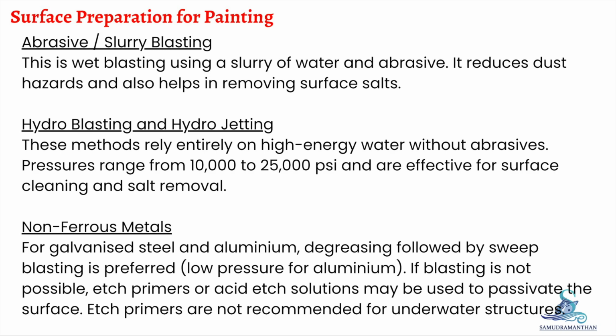Hydroblasting and hydrojetting take abrasives out completely. These methods rely entirely on the energy of water striking the surface, with pressures ranging from 10,000 to 25,000 psi. They are very effective for cleaning surfaces and removing salts. For non-ferrous metals, the approach changes slightly. For galvanized steel and aluminium, degreasing followed by sweep blasting is preferred, at low pressure in the case of aluminium. If blasting is not possible, etch primers or acid etch solutions may be used to passivate the surface. However, etch primers are not recommended for underwater structures.